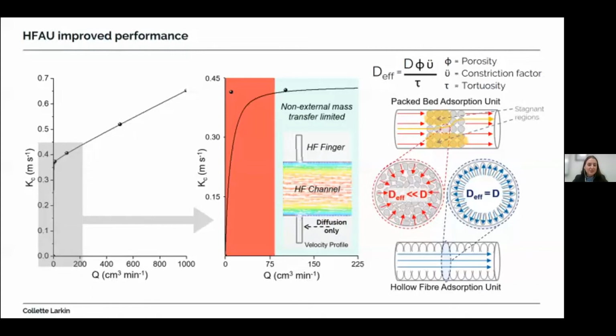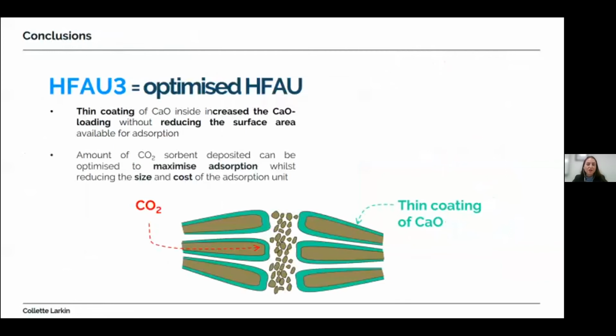And so to conclude, this work provides critical information to advance the design of future hollow fibre-based adsorption units. The thin coating of calcium oxide inside the fingers of the hollow fibre adsorption unit 3 increases the calcium oxide loading without reducing the surface area available for adsorption. This demonstrates that the amount of CO2 adsorbent deposited can be optimized to maximize CO2 adsorption whilst reducing the size and cost of the adsorption unit.